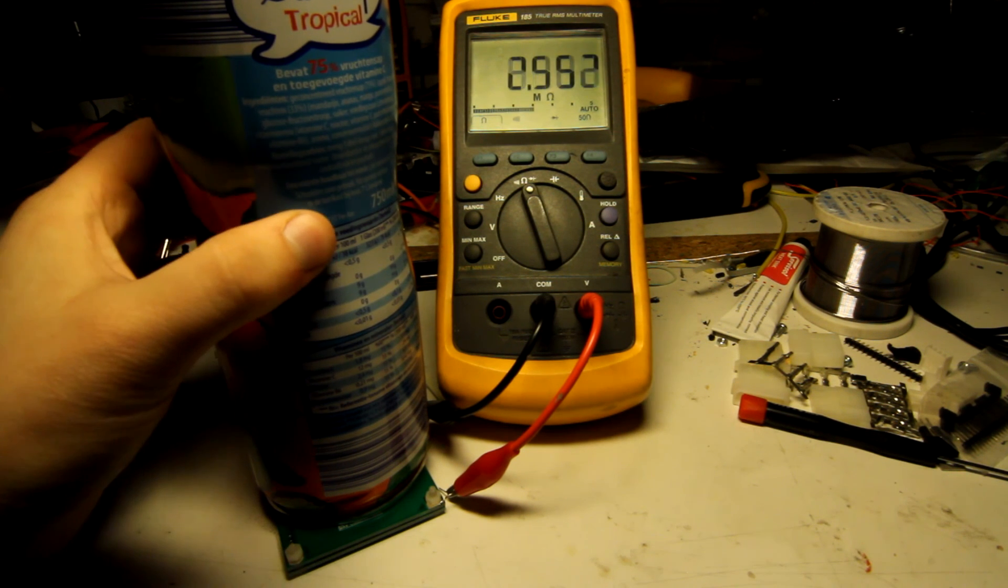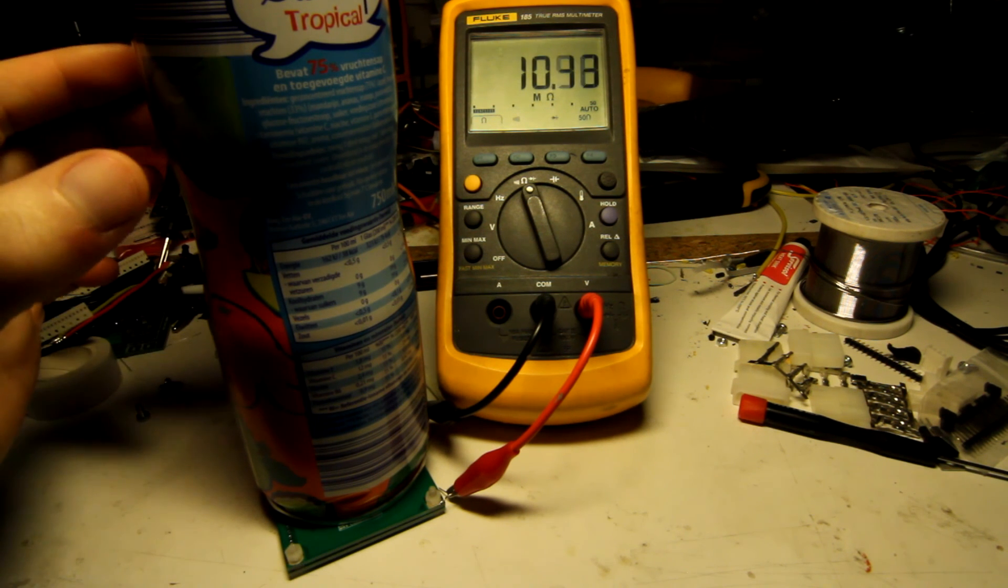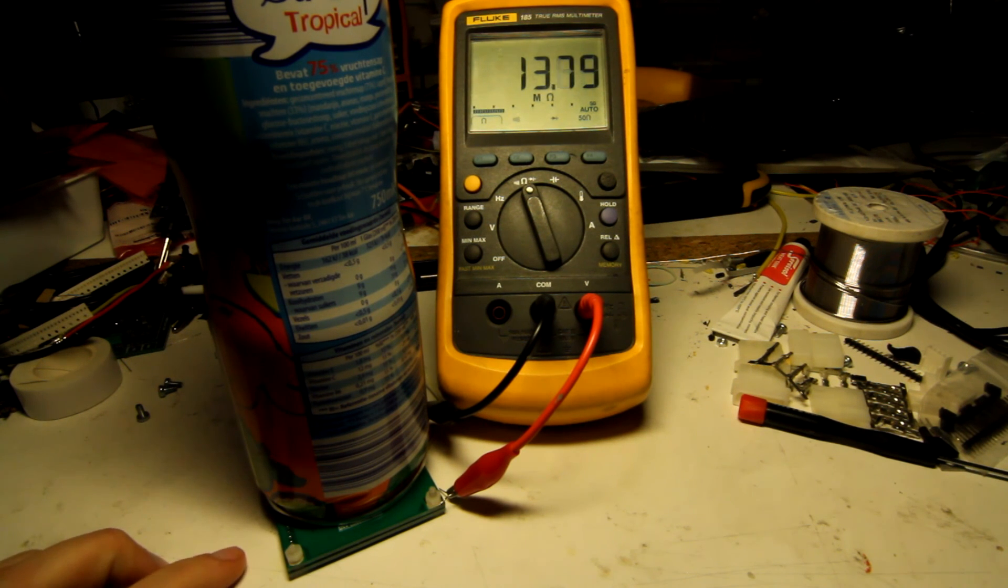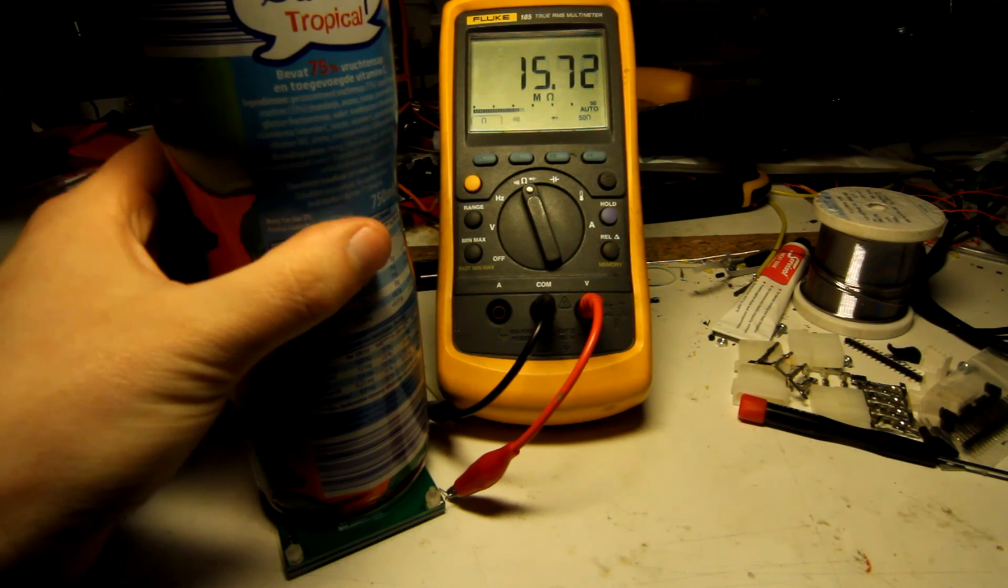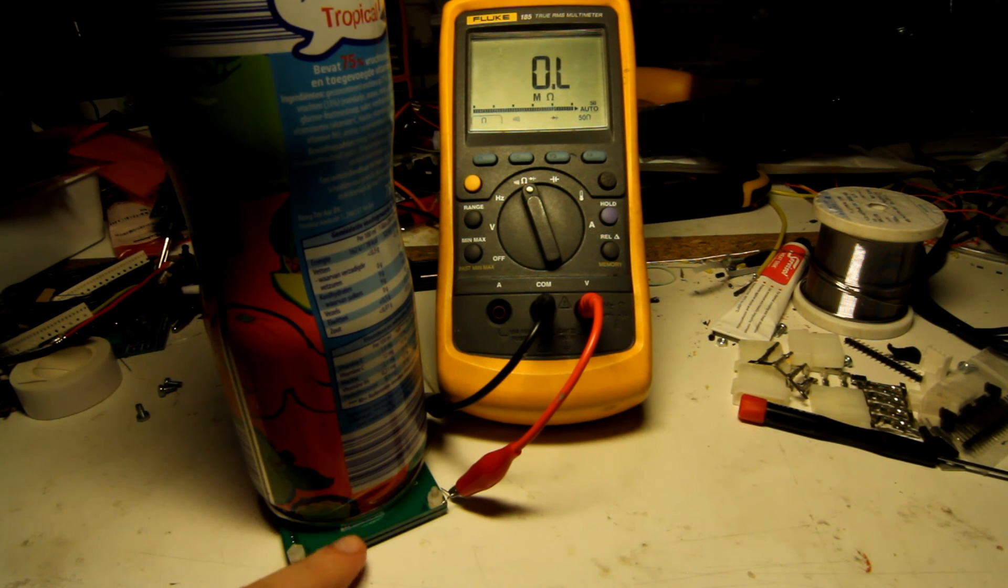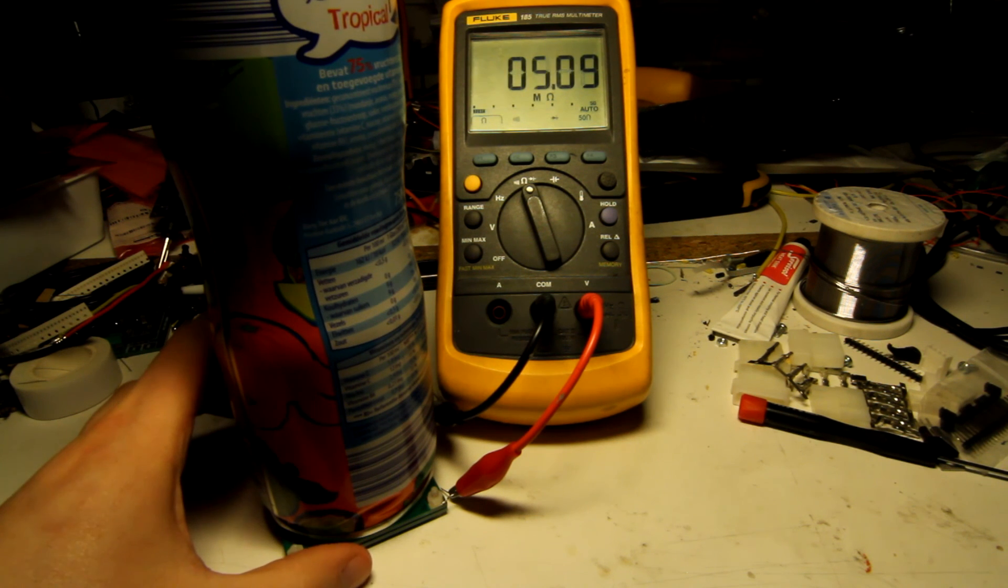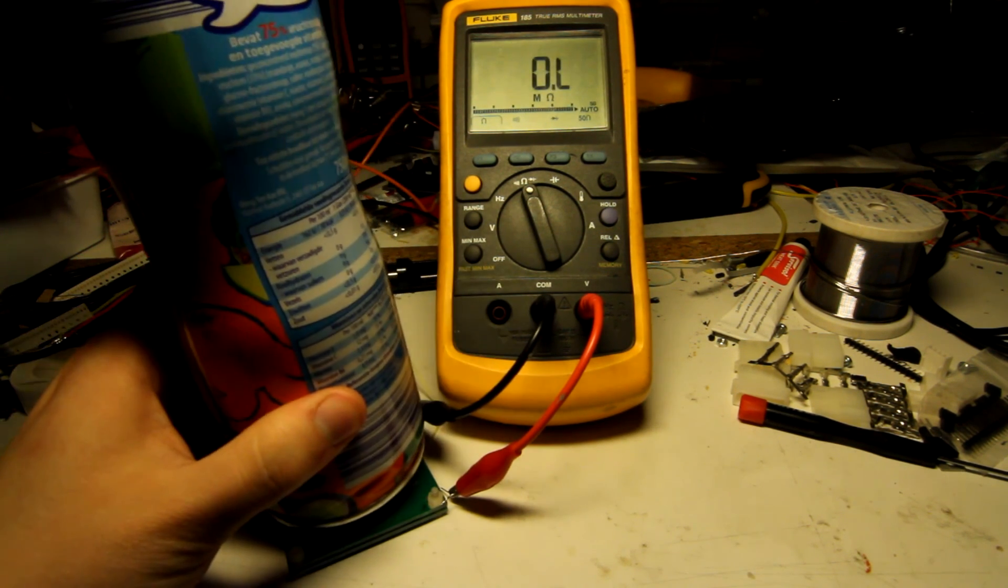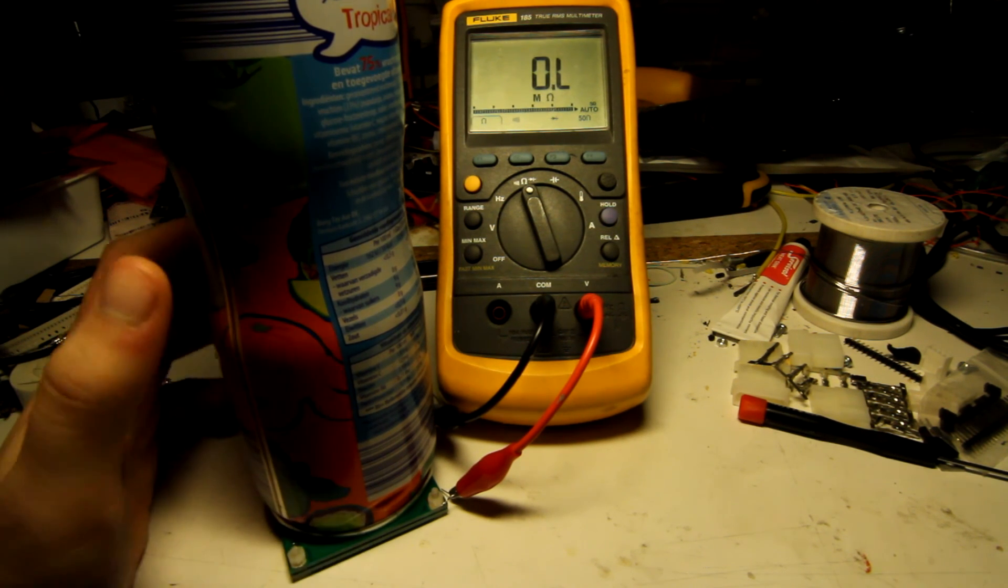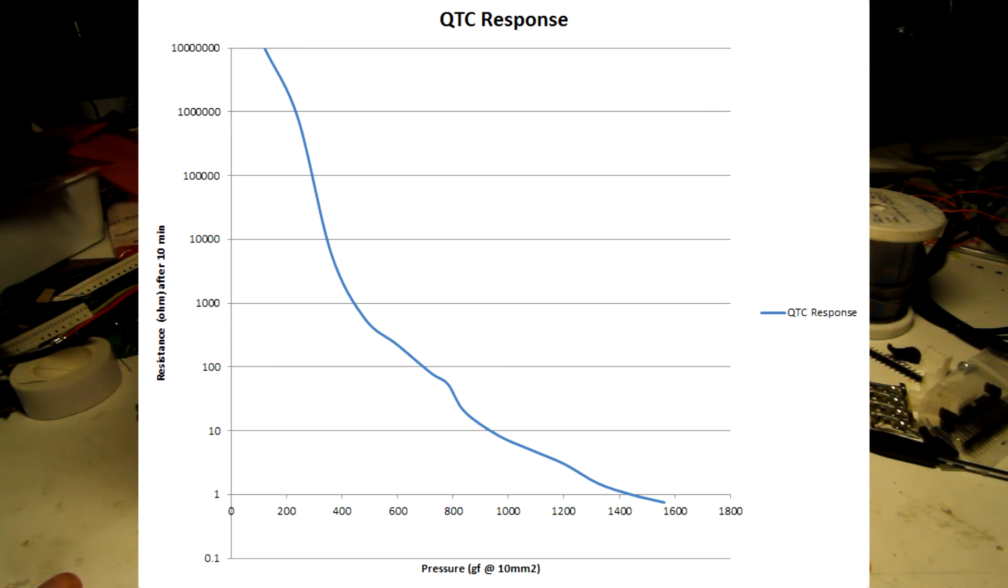Now, one thing I've found is that if you just remove the load and kind of reset everything, it does tend to reset to some neutral value fairly well. So one possibility to use these QTCs for linear force measurement is to add the load, wait for a certain number of seconds, then take a measurement, then remove the load again and just repeat. And I've actually gotten reasonably good results with that. I will show you a plot on the screen of the resistance versus force that I found.